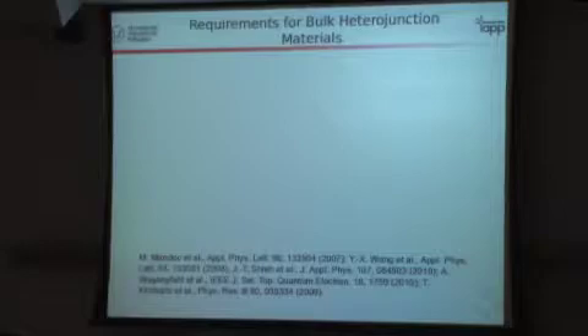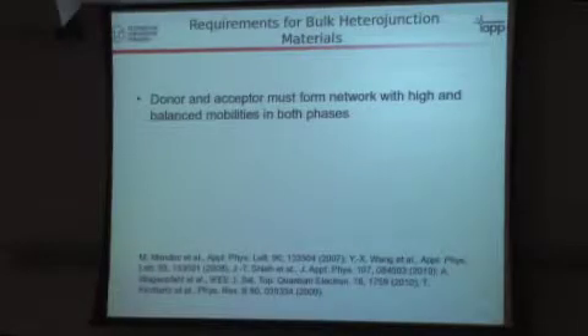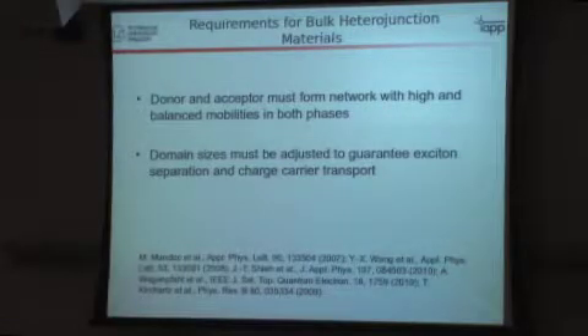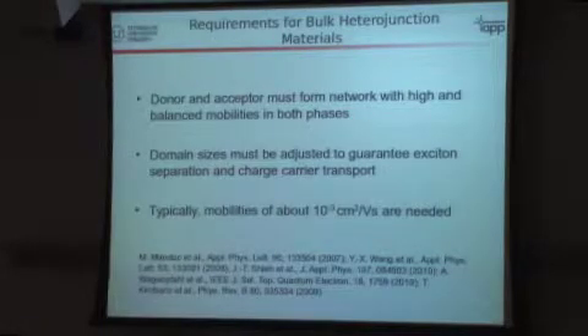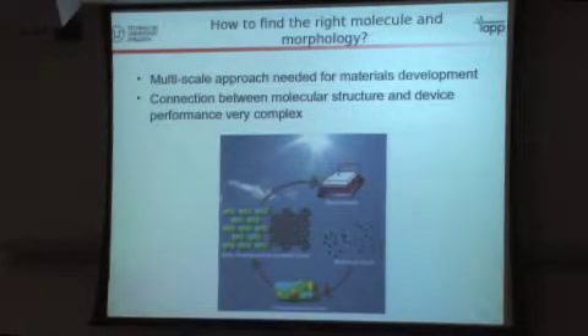Now let me come in more detail to which materials we need. We have this bulk heterojunction, and what we need to do is form a network with high and balanced mobilities. We must adjust the domain sizes to have at the same time good separation and good transport. And the calculations show that we need mobilities of about 10 to the minus 3, which sounds fairly low, but actually in this bulk heterojunction is already a pretty high value. Now, even what an optimum mobility is, is not clear, and I want to discuss that with some results I'll show you in a second.